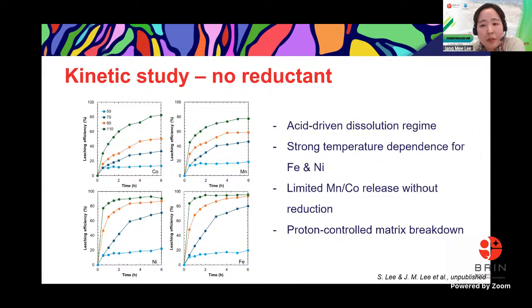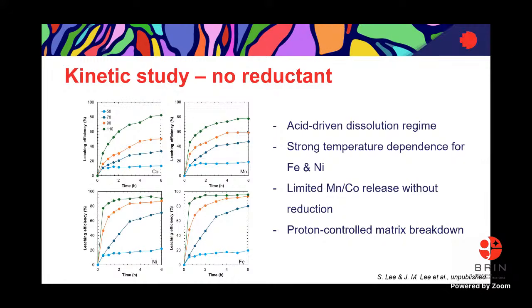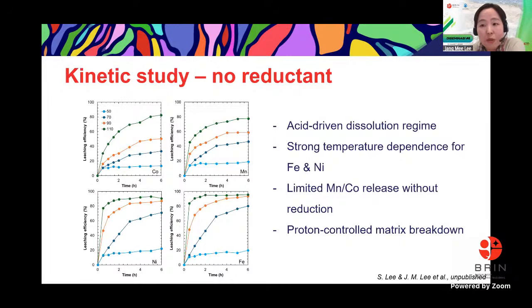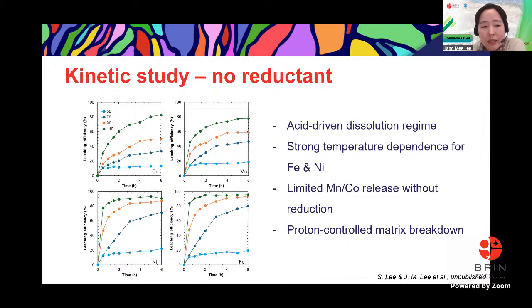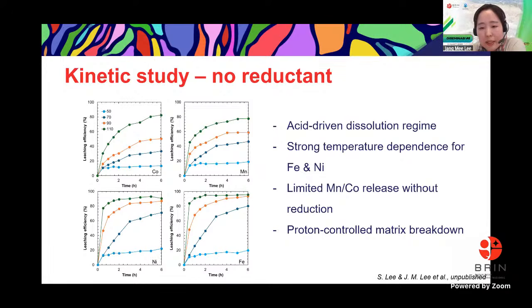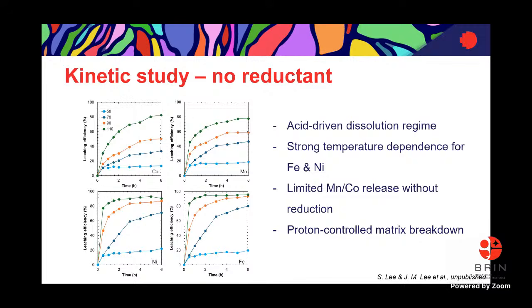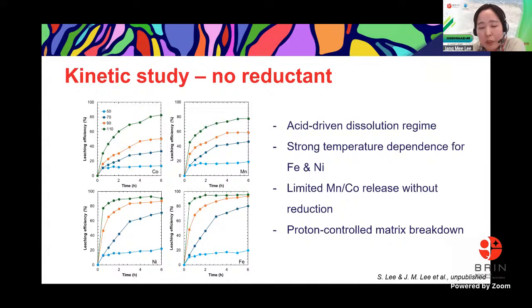Thank you. First of all, this is not Fe2O3. This is not hematite. This is goethite. My understanding is goethite is a lot easier to dissolve compared to hematite. Nickel is co-associated in the goethite crystal structure. I checked another type of ore that has a major hematite crystal structure, but under the same condition it shows a completely different result. So I think the iron phase is important as well. And also, this atmospheric nitric acid leaching is very, very good for nickel extraction.